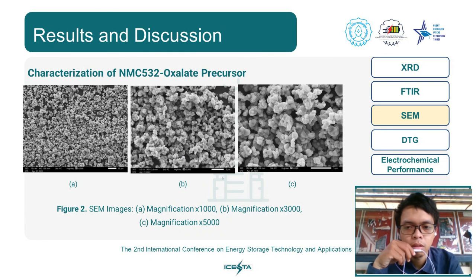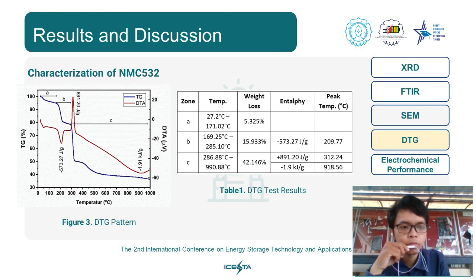And here is the characterization of the NMC 5:3:2 oxalate precursor using scanning electron microscopy at various magnifications. The calcination and sintering process of NMC 5:3:2 material was analyzed by thermal gravimetry, resulting in 3 reaction interpretation zones. In Zone A, the stage 1 dehydration process occurs, and in Zone B, the stage 2 dehydration process occurs. Zone C is the zone where the calcination and sintering process occurs.